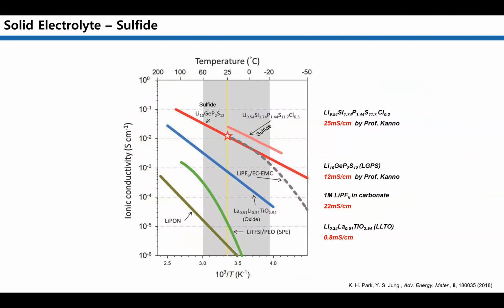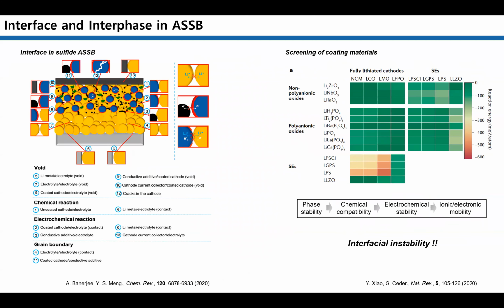At this point, I would like to say the ionic conductivity by itself is no longer a barrier to developing solid-state electrolyte systems. In our solid-state lithium metal batteries, the interfacial instability due to the nature of the ionic conduction system by solid-solid contact is a bottleneck. Although this problem is also present in liquid systems, it is particularly challenging in our solid-state batteries due to the kinetics difference arising from the different lithium-ion transport mechanism. The complexity of the interface within our solid-state battery systems also presents challenges.